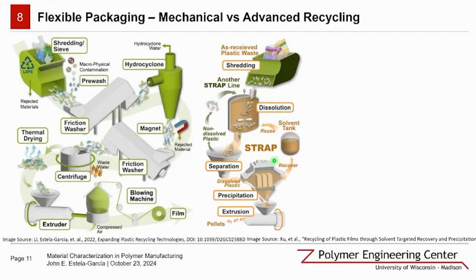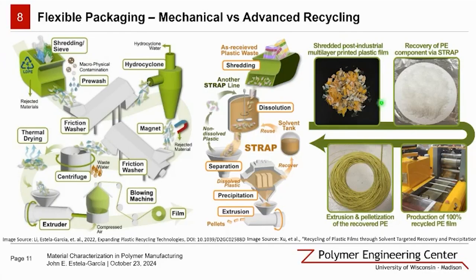STRAP is capable of handling more complex waste streams and potentially yielding this higher quality recycled materials that are required for our polymer products. This final infographic demonstrates STRAP in action. We've been able to showcase this. We have here post-industrial multi-layer printed plastic film. After being subjected to STRAP, we have recovered the polyethylene components. We were able to then extrude and pelletize this recovered PE and then produce a 100% recycled polyethylene film at the factory. So this real-world application showcases the potential of advanced recycling in creating high-quality materials.